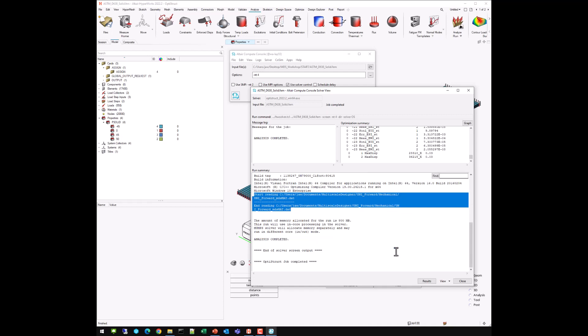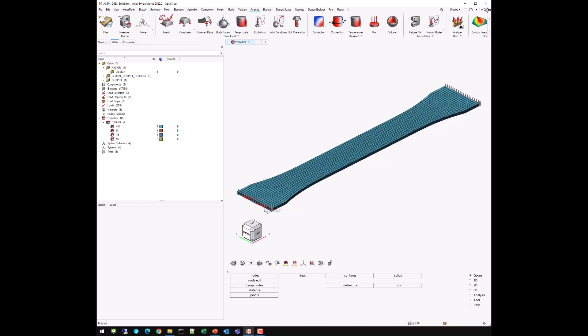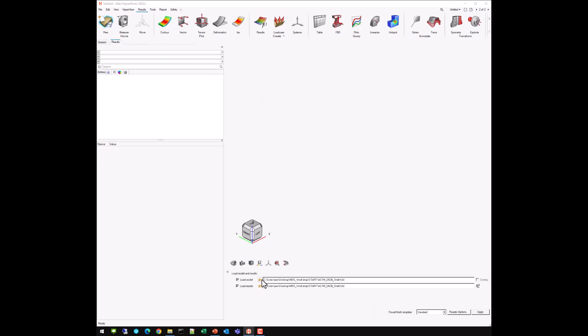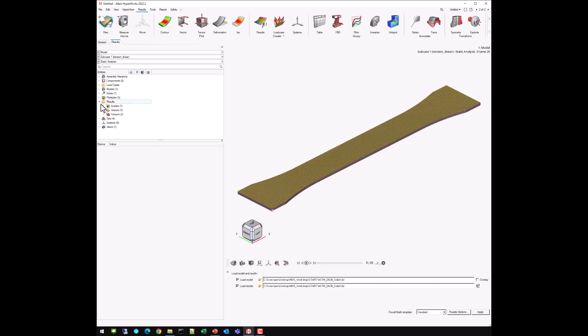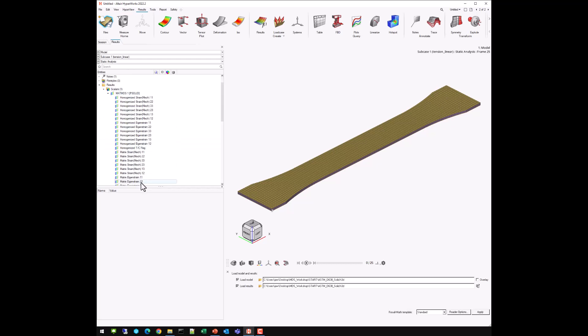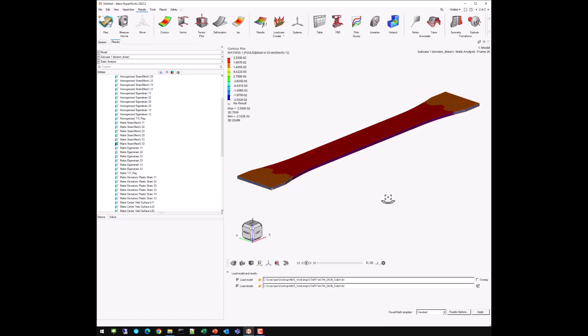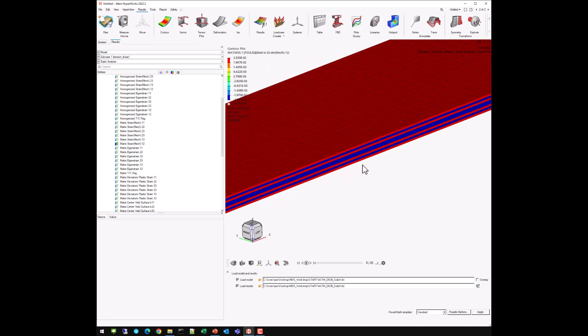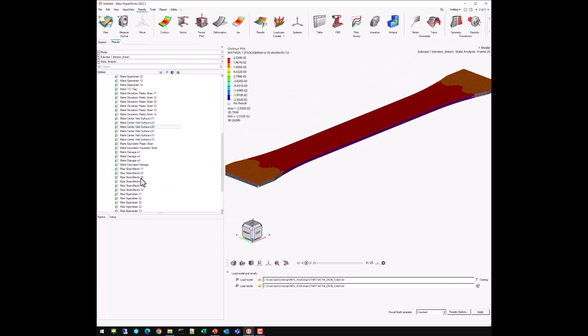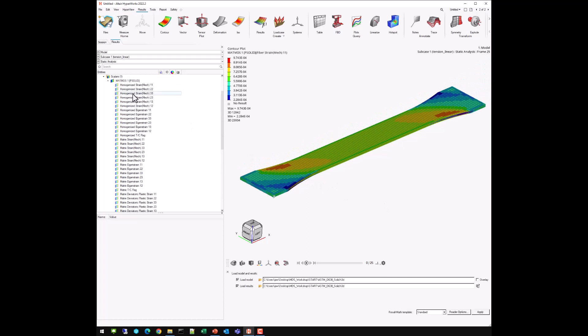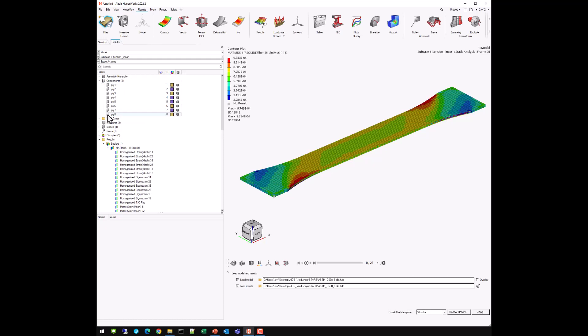The solid model analysis completes. We close the solver window, go to the post-processor, and load the H3D solid results. Nothing is different from the shell model — under Results > Scalers, we again see the MAT_MDS results. In the linear run, we can look at the matrix shear strains and see the plus-or-minus nature of the shear strains in the ±45 plies. We can also look at the fiber strain — the top layer is the minus 45. By removing individual solid layers from view, we can peel off successive plies: the 45, another minus 45, and so on.